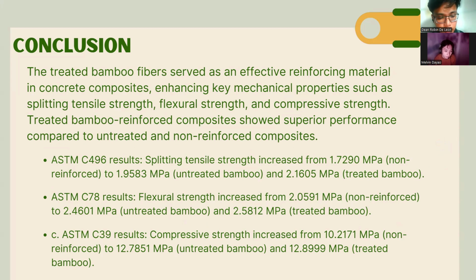The treated reinforced composites showed superior performance compared to untreated and non-reinforced composites. According to the results of ASTM C496, the splitting tensile strength increased from 1.73 megapascals to 1.96 and 2.16 megapascals. ASTM C78 revealed that the flexural strength increased from 2.06 to 2.46 and 2.58 megapascals. And the ASTM C39 results revealed that the compressive strength increased from 10.22 to 12.79 and 12.9 megapascals, with the treated bamboo fibers exhibiting the highest strength.